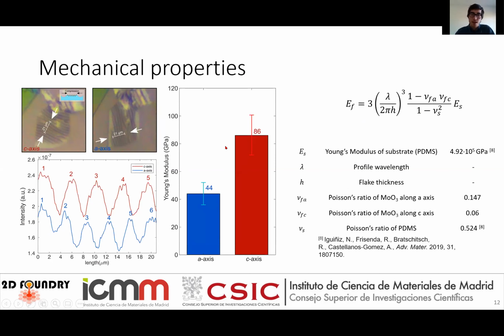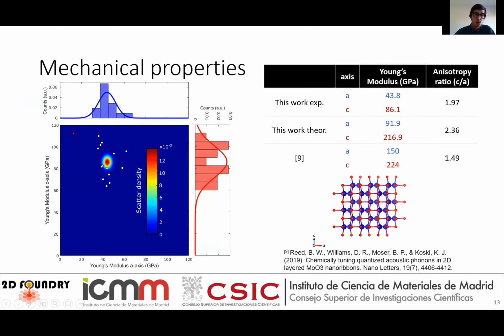We have found these values of Young's modulus on these two axes. And we have also done this with several flakes, and this is a scatter density plot with 14 different samples of molybdenum trioxide flakes. Fitting these samples to a Gaussian function gives you this plot. It could be a little bit more precise, but it is very well performed. And you can compare these values with other ones published.